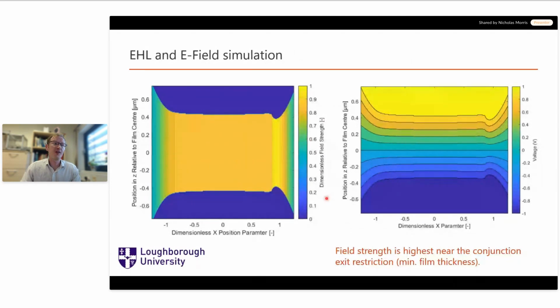And I've used a dimensionless field strength here, so it's just normalized to the smooth surface, and it's the same for all of the other figures. So it's normalized by the minimum film thickness and the voltage which is applied across the contact. So when you look at all of the figures, if it says 1, then that's exactly the same as the smooth surface between the minimum film thickness. If it's higher than that, then whatever's been added to the model, so the roughness, for example, or an electrical discharge machining pit, has either increased or decreased it relative to the smooth case, and what we would commonly assume as a typical value for when breakdown would occur.